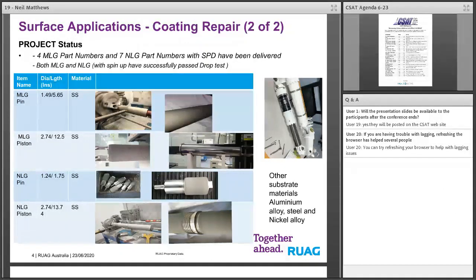So as you can see, we've put it on a whole range of parts, about 11 parts in all. Some of them are quite large or long. We have deposited it down as a single coat. The challenge has not been the deposition. The challenge has been, in fact, the post-deposition machining or grinding. That's given our folks some challenges, but we've been able to successfully deliver that. So that is effectively an OEM approved deposition on a new aircraft type. So that's quite significant from where we see it.